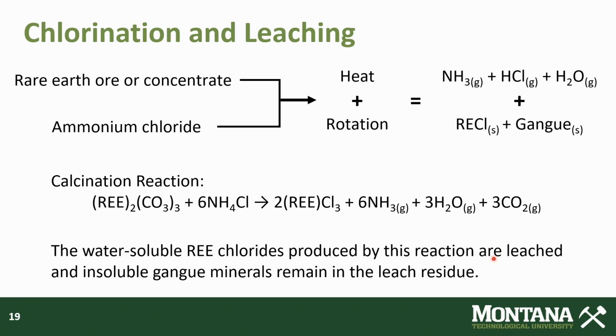So the key part is the rare earth element chlorides. What's neat about those is they're highly soluble in just plain old water. So we can do a simple water leach and get very high extraction efficiencies, meaning that a high percentage of the rare earth chlorides are going to enter solution. Hopefully we can minimize the amount of gangue and other constituents. That's something we're analyzing right now. We do know that we're going to have an iron issue, and that's something we'll deal with downstream.